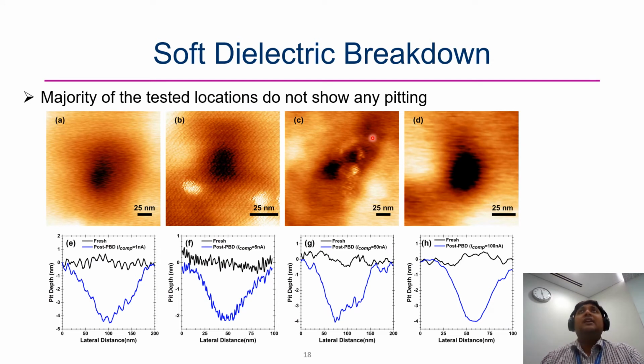The earlier experiment was done under the hard breakdown condition, but in actual circuit conditions, we rarely reach those current levels. So our interest was to look at the soft dielectric breakdown, and when we say soft breakdown, the current remains relatively very low, for example, hundreds of nanoamps. Also the earlier experiment was done in ambient, so we wanted to verify what happens when we change the conditions, for example ultra high vacuum.